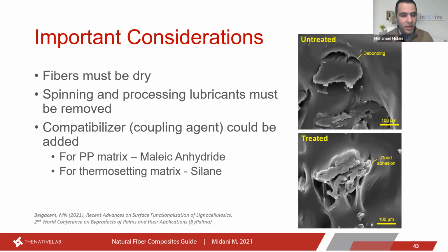As you know, the matrix is responsible for transferring the load. So if there is no good interface, the matrix will not be able to transfer the load, and consequently, it will result in lower mechanical performance versus a natural fiber composite with a coupling agent. So we're having an excellent adhesion between the fiber and the matrix. The fiber is locked inside the matrix. It's not allowed to pull out of the matrix. So here we have very good load transfer efficiency.